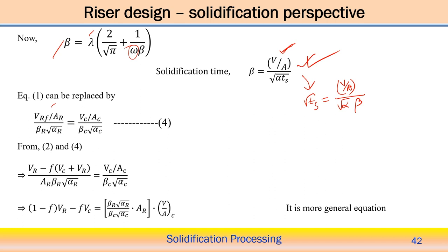So therefore in this case, with the similar analogy, we follow equation 1. Equation 1: the volume by area ratio for the cast and the riser will be the same. So if we incorporate the effect of beta, here also in both cases the solidification time will be the same. So in case of the riser, this can be V by A riser, alpha riser, beta riser, okay.